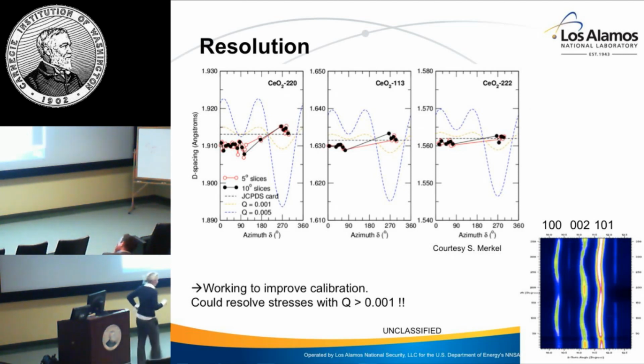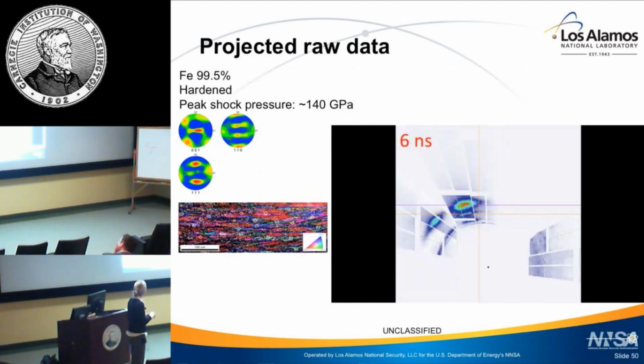So here's an example. I'm not all the way up at the highest pressure point, but this is something like 140 GPa. Here is a movie, slices, snapshots of the diffraction, and you can see a BCC structure here that starts, and you immediately get the HCP triplet, and some changes in the preferred orientation as a function of time, okay? And all of these shots are executed at the same high pressure temperature condition, okay?